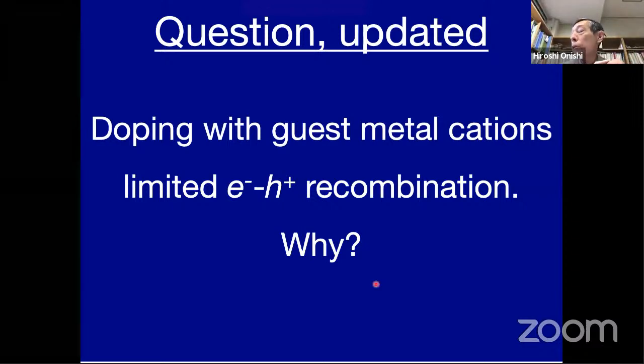Doping with guest metal cations, strontium doping of sodium tantalate, limited electron hole recombination. Electron hole recombination is a way to reduce the number of electrons. So by using infrared absorption, we found the number of electrons much enhanced by strontium doping. So this means strontium doping limited electron hole recombination. So our question is updated. Why did this happen? Why did strontium doping limit recombination? So to